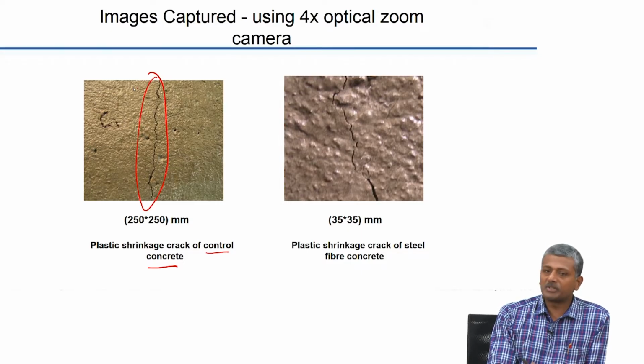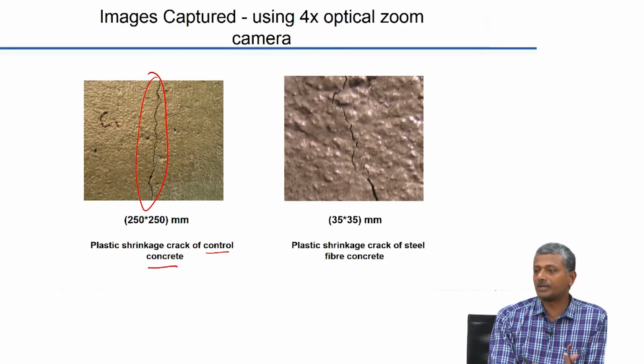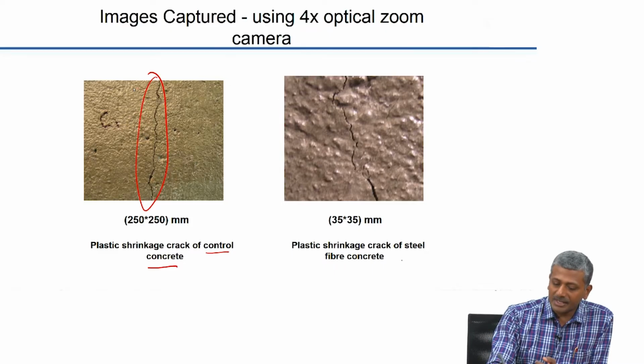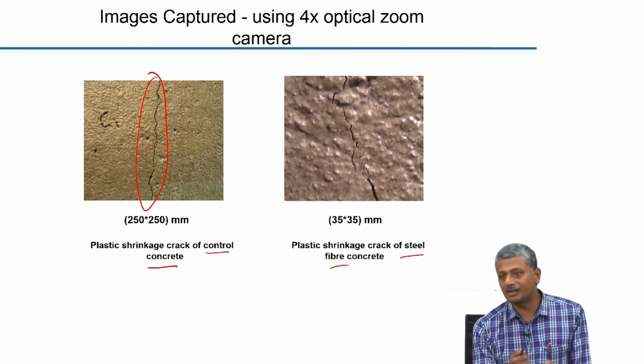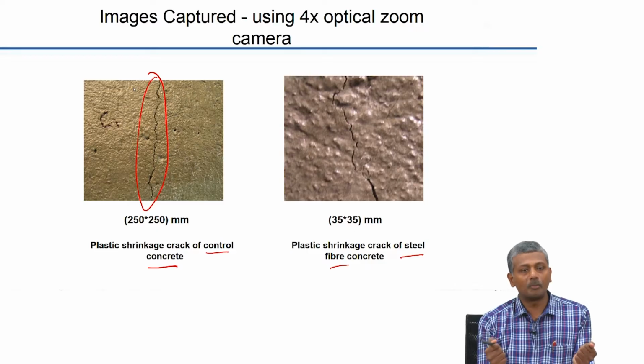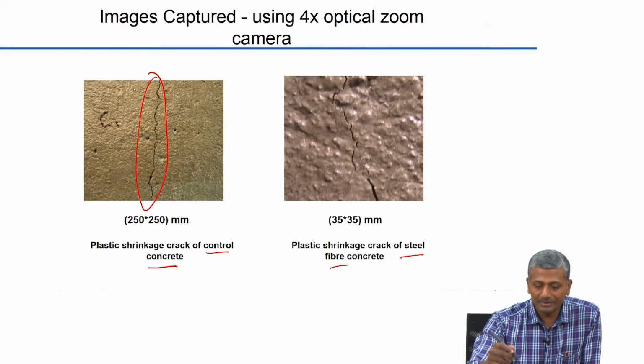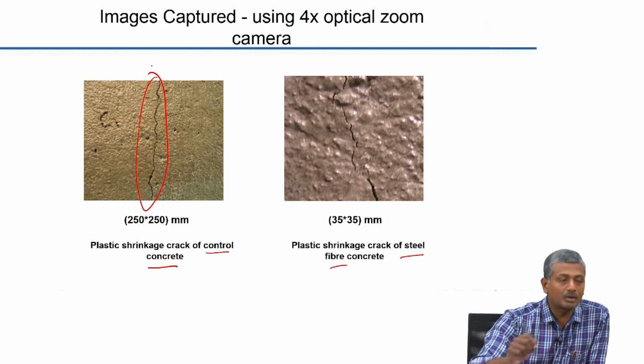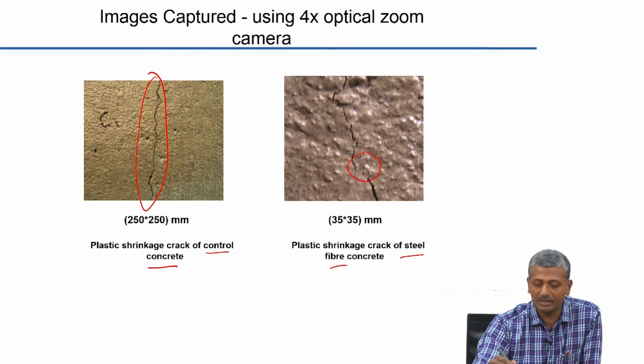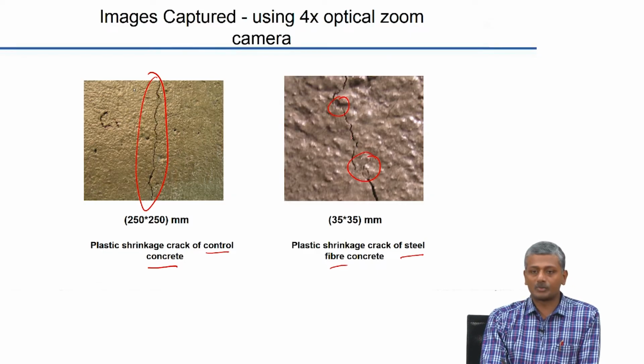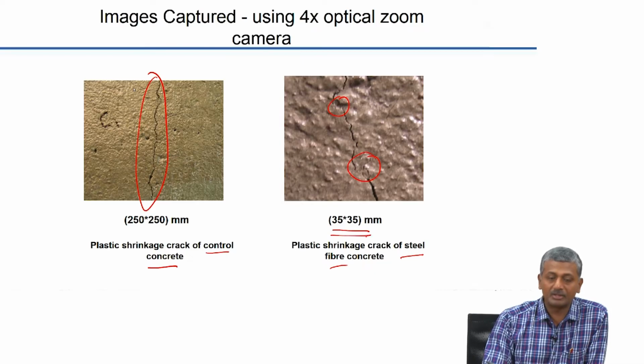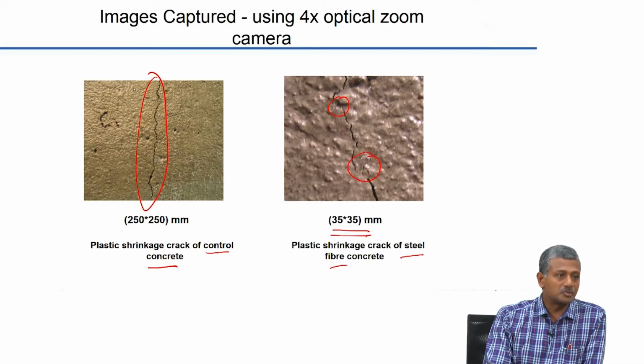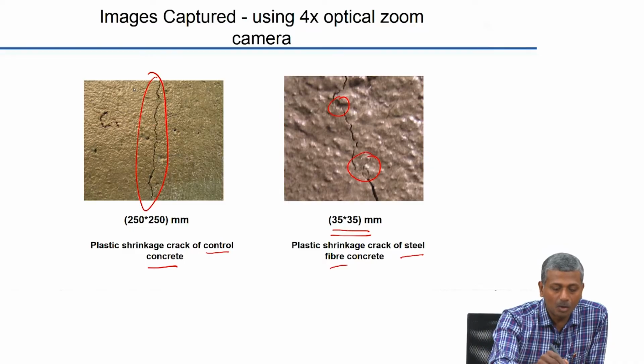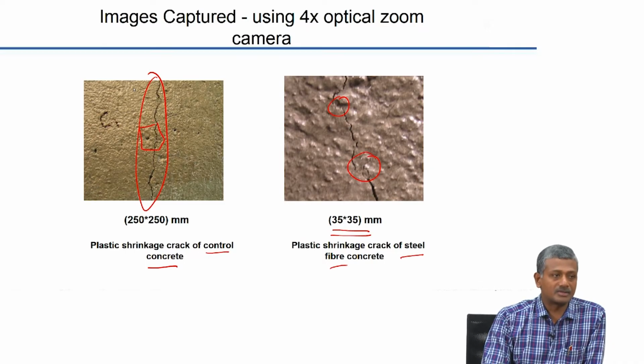Okay. Of course, you can do image analysis on this and determine the extent of crack area, maximum crack width and all the other crack related parameters. Now, for the steel fiber concrete, the presence of fibers obviously reduces the propensity for crack opening up, and as a result of that, the cracking was not uniform all across the stress riser, but it started deviating at some locations, and you can see some branching of cracks, and overall the crack width is also much smaller. Please note that this is only a 35 by 35 millimeter area that has been imaged in this picture, and that is a very small part of this entire stress riser that we are showing on the left.